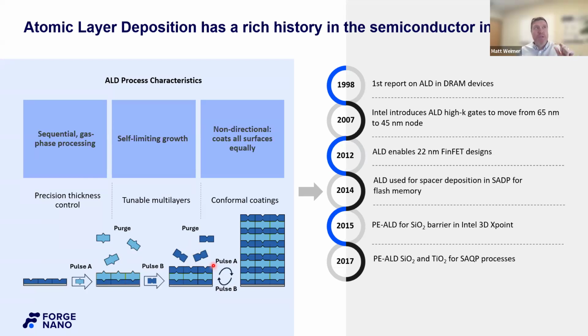It's pretty neat because we get a digital amount of film with each cycle. That's typically on the sub-angstrom scale, so maybe you get an angstrom. There are a couple of processes that are a little more, but you get very fine thickness control that you can then build up into the film thickness that you desire. So there's a lot of cool things that come out of this. I'll talk about that on the next slide.